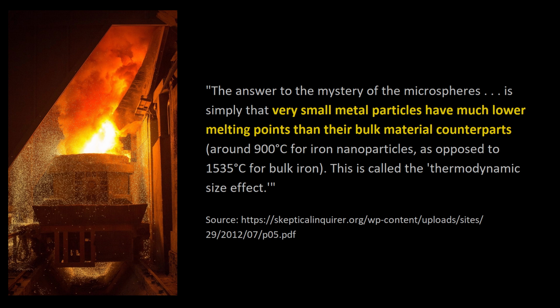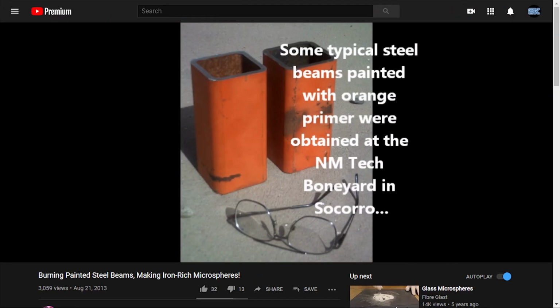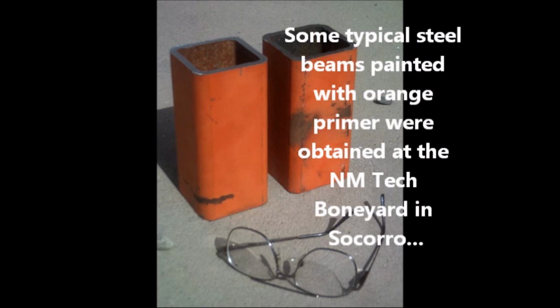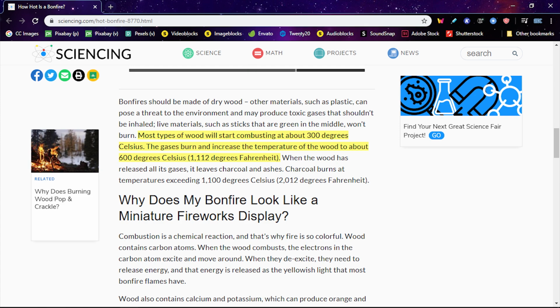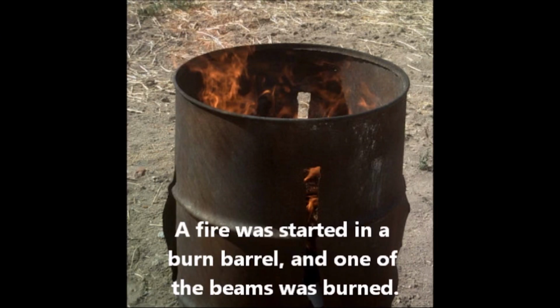Quote, "the answer to the mystery of the microspheres is simply that very small metal particles have much lower melting points than their bulk material counterparts, around 900 C for iron nanoparticles, as opposed to 1535 C for bulk iron. This is called the thermodynamic size effect," end quote. He also shows that if you burn steel beams coated in primer paint in an ordinary wood fire, which does not reach the melting point of bulk iron, you can nonetheless create iron microspheres.